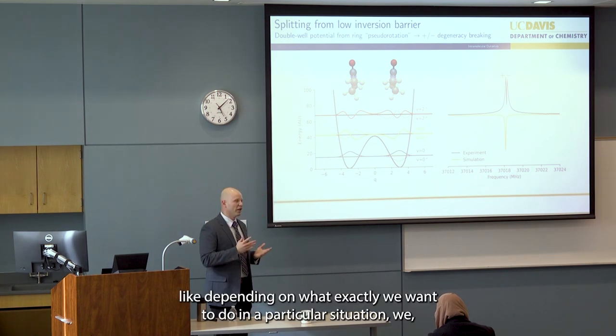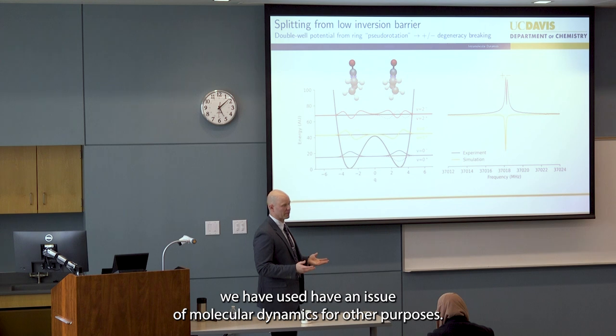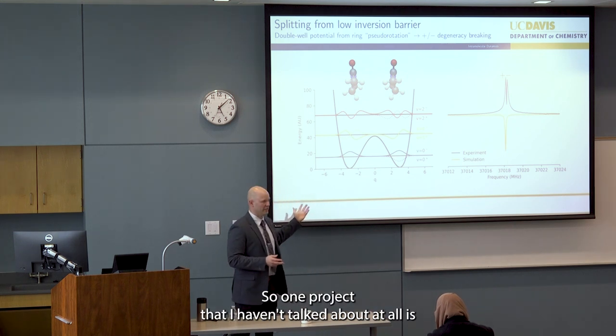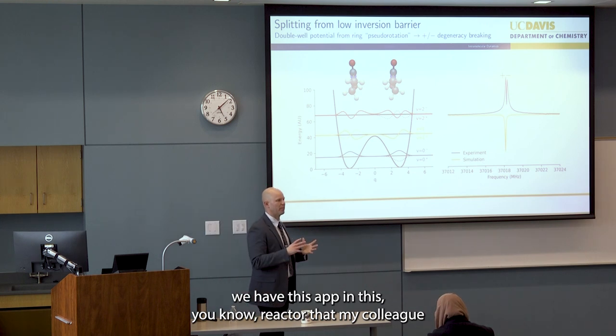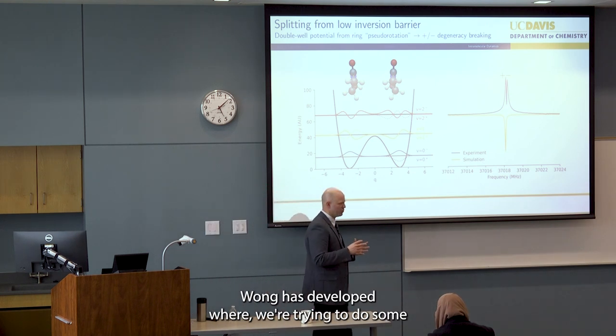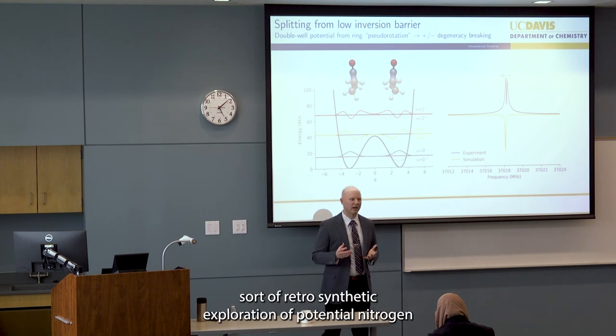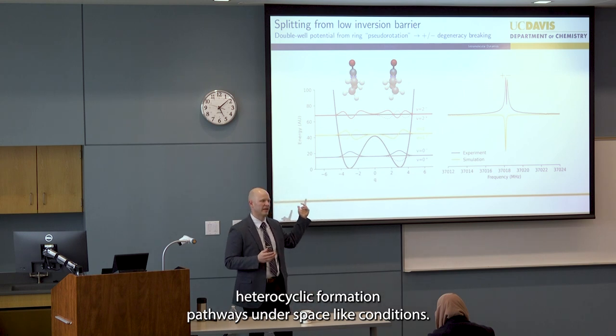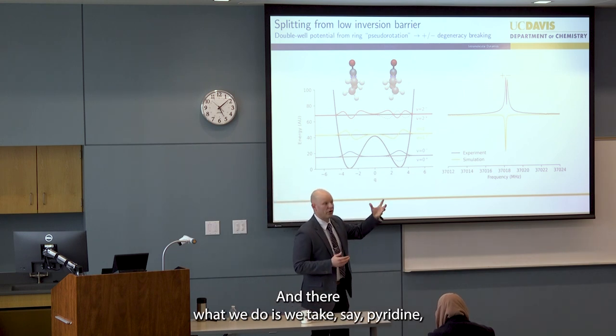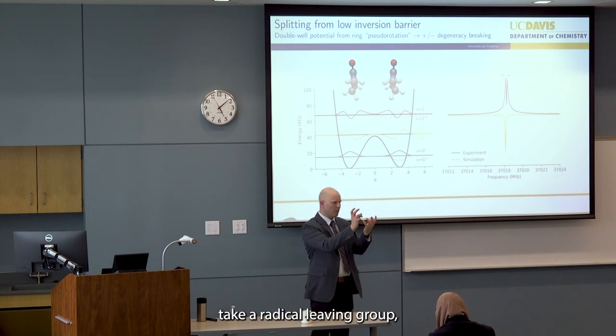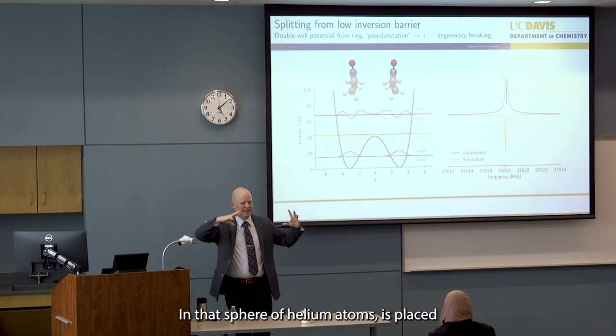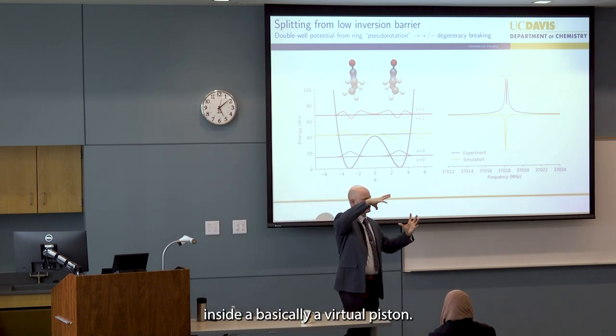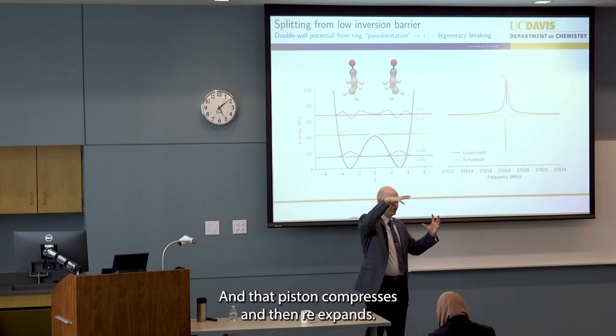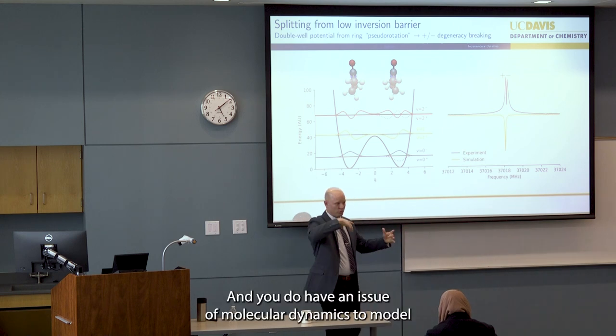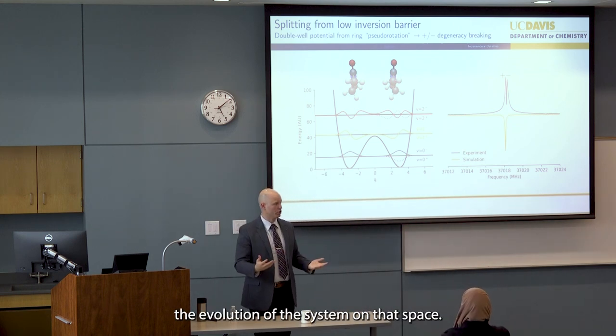However, depending on what exactly we want to do in a particular situation, we have used ab initio molecular dynamics for other purposes. So one project that I haven't talked about at all is we have this ab initio nanoreactor that my colleague Li Ping Wang has developed, where we're trying to do some sort of retrosynthetic exploration of potential nitrogen heterocycle formation pathways under space-like conditions. And there what we do is we take, say, pyridine, take a radical leaving group, put them together inside a sphere of helium atoms. And that sphere of helium atoms is placed inside a virtual piston. And that piston compresses and then re-expands. And you do ab initio molecular dynamics to model the evolution of the system on that space.